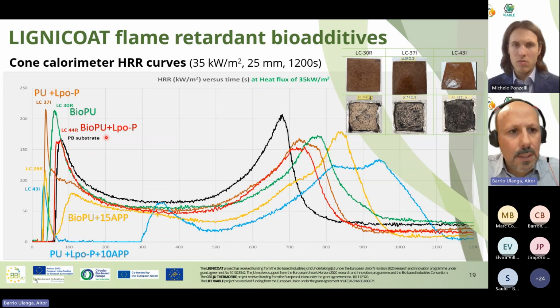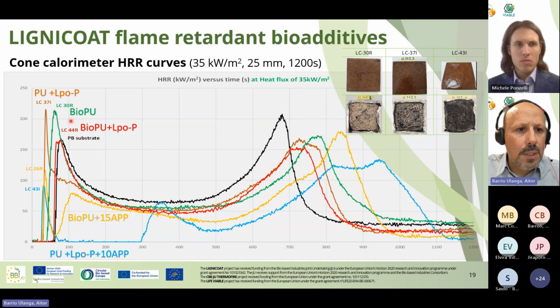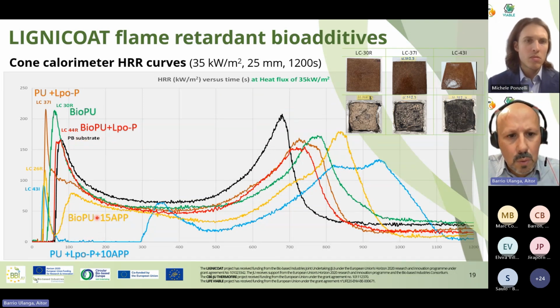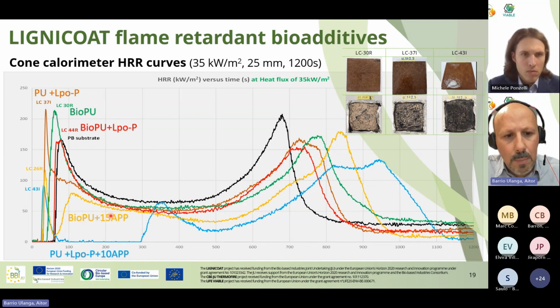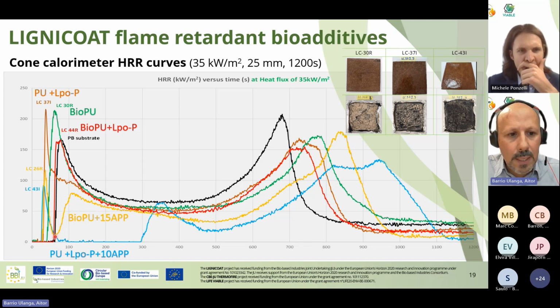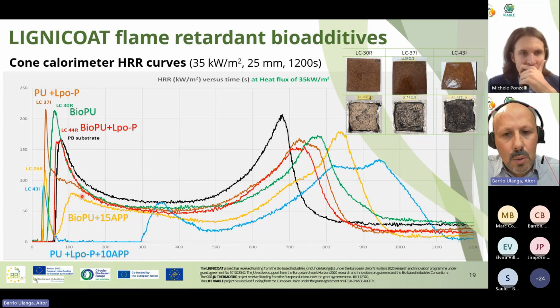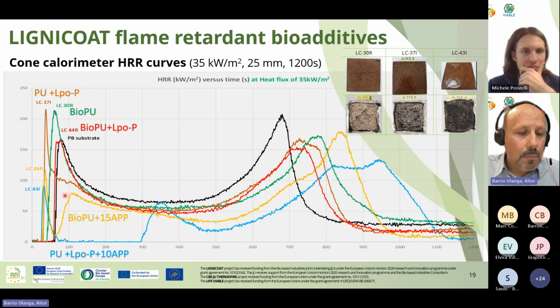We obtain good results, but it's not enough. If we move to only ammonium polyphosphate, we see that we decrease the ignition a lot. We create a barrier that protects, but not enough to avoid ignition of the substrate. So we reproduce the curve of the substrate in yellow.